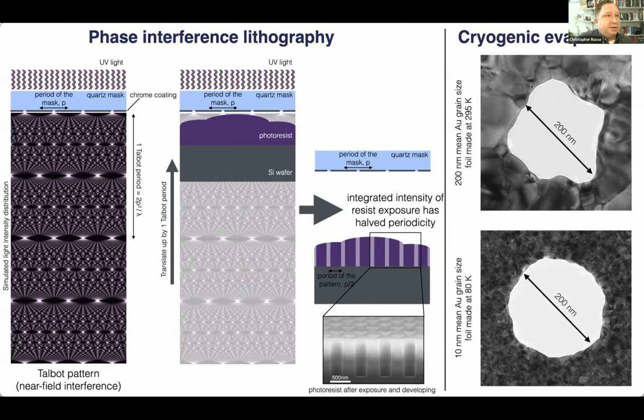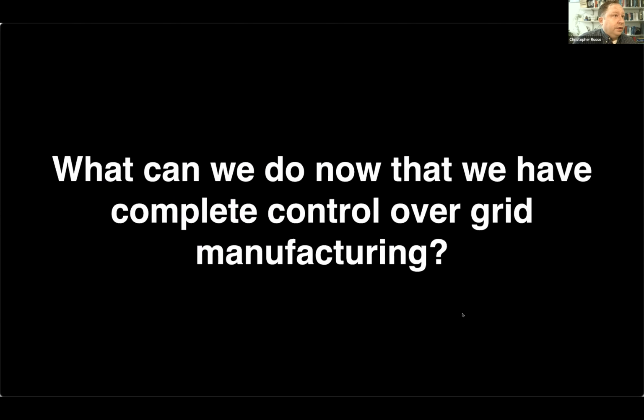And so this was not sufficient to make nice, small, round holes, which we wanted to put these specimens in. So we developed an evaporator that had a cryostage, allowing us to reduce the grain size of the gold crystals by an order of magnitude or more. And then that allowed us to make these very nice round holes for the specimen. So now that we have these grids, what can we do now that we have complete control over grid manufacturing?